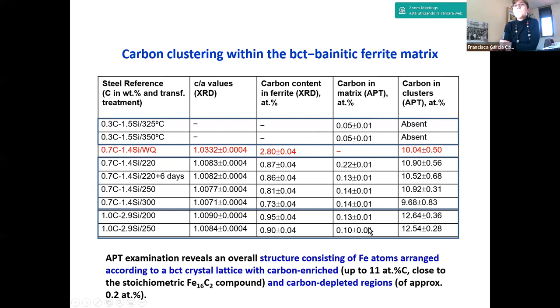When we have this significant amount of carbon in the ferrite, we detect the carbon clustering and we detect significant tetragonality, but never of the level of a quenched martensite. What is really interesting is that the carbon content of those clusters compares quite well with an iron-carbon compound that was also reported in the literature as a precursor or an embryo of the nucleation of metastable carbides such as epsilon carbide during the evolution of the structure of martensite at the very early stage of tempering.